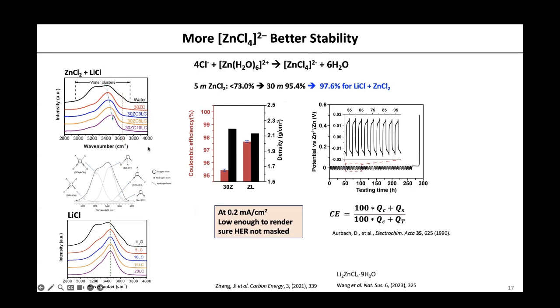If you say, oh, I don't think that is very convincing, because maybe it's just due to the lithium chloride alone, so we did that. We just added lithium chloride to pure water, making it extremely concentrated, 20 molar lithium chloride. Look at this peak. It's not shifting. So by having more chloride ions or lithium ions, you are not going to shift this peak. Comparing the two salt solutions, the only difference is that we have a lot of zinc tetrachloride here.